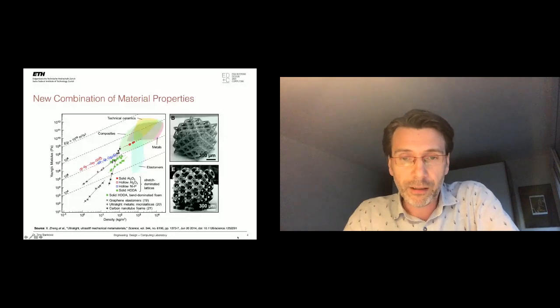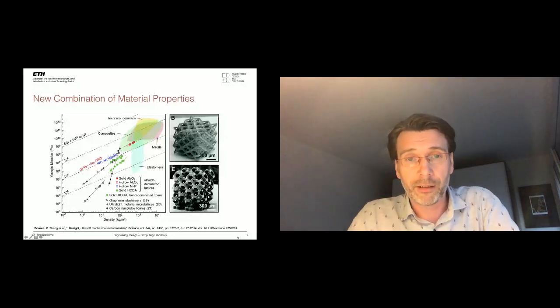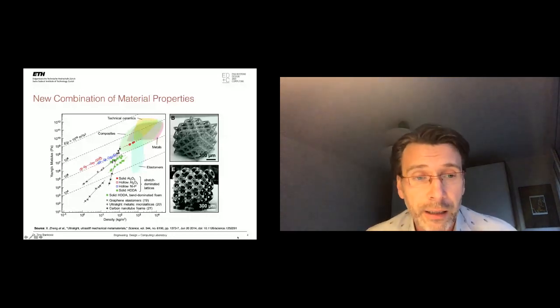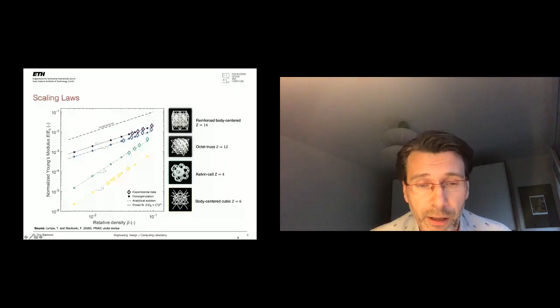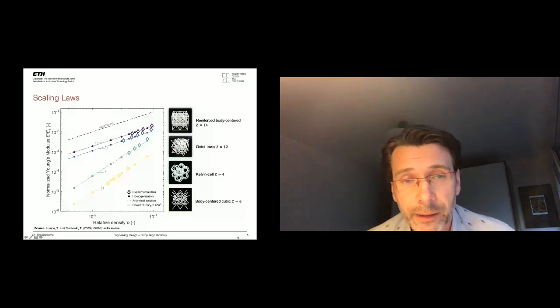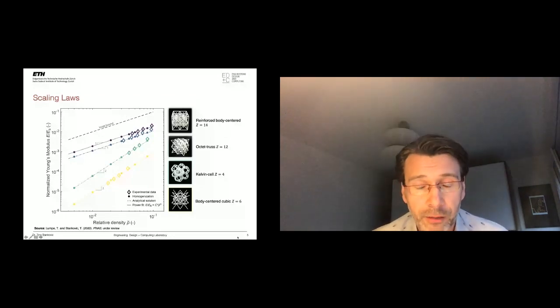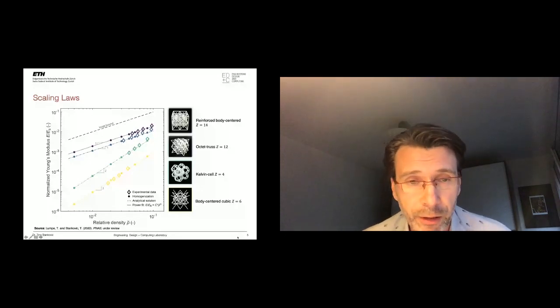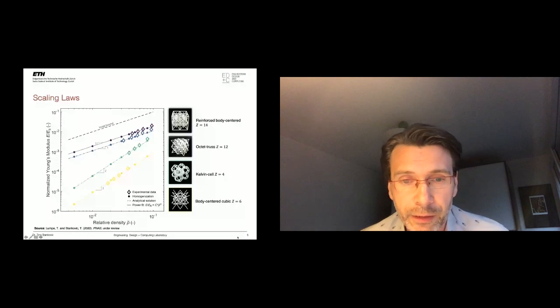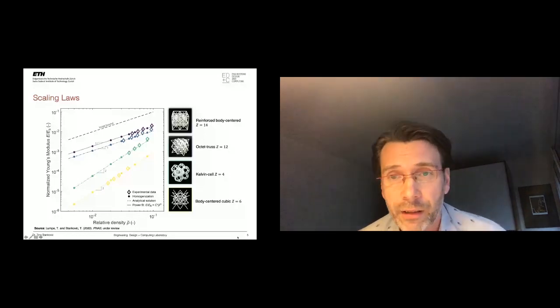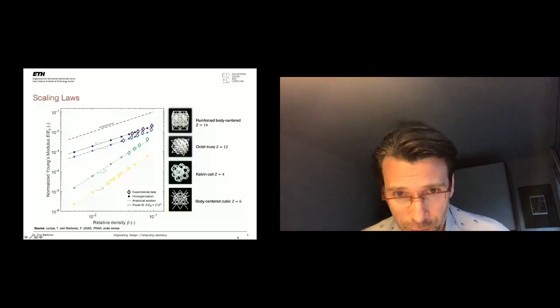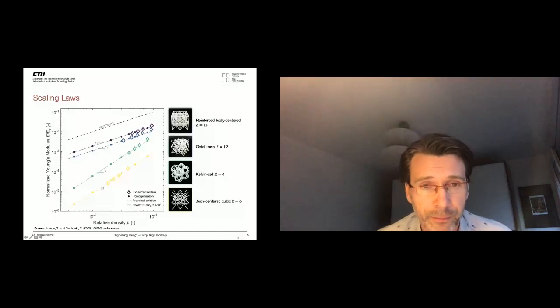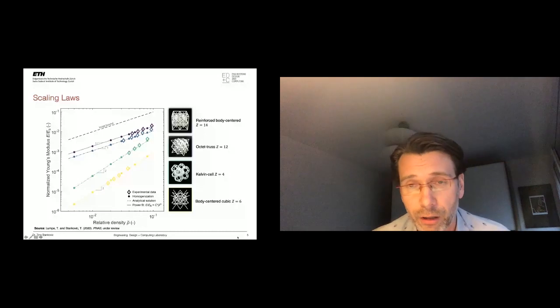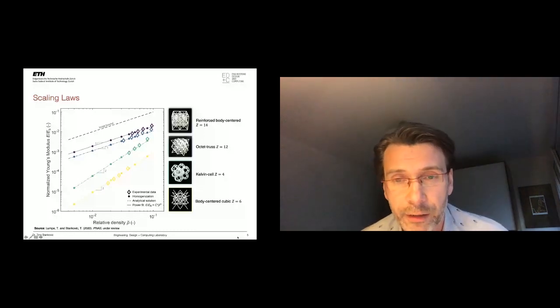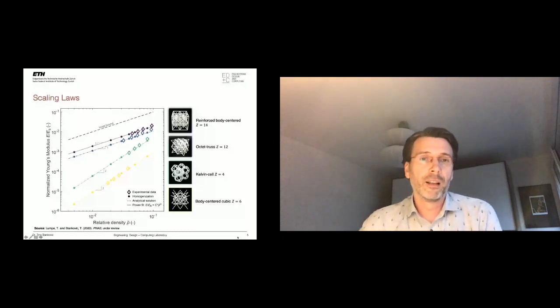that can appear in designing metamaterials. Of course, the behavior of material is not only linked to the geometry, it's also linked to the topology. In this simple chart, I showed the normalized Young's modulus over relative density plot. What I'm trying to show is that different scaling laws describe the basic mechanical behavior of each of the architected materials. For instance, if the scaling factor equals 1, as we discussed, then we are talking about stretch dominated structures. And if the scaling factor is above, in this example 2, then we can talk about bending dominated structures. We also discuss the mechanical failure in these materials, whether they are dominated.